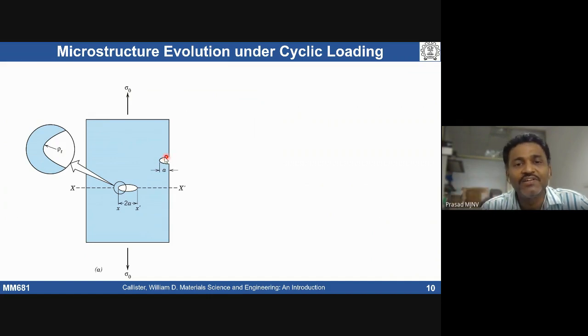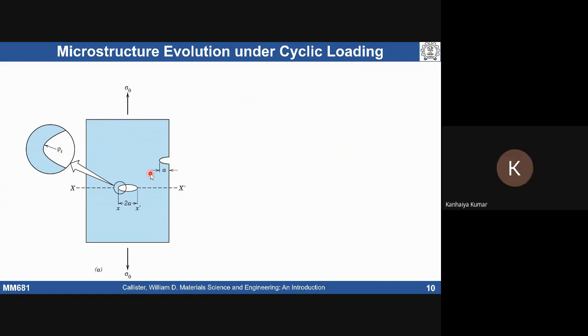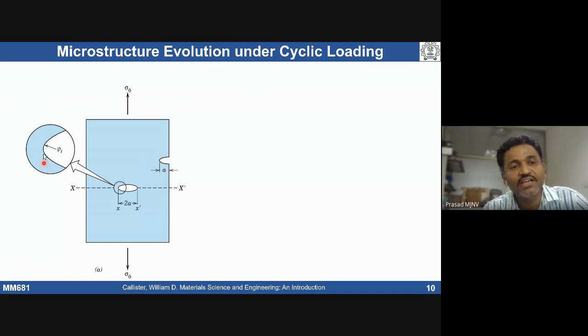Now assume that a crack has been formed on the surface. If I look at the stress in front of the crack tip, is it going to be higher or lower than sigma naught? I hope some of you already had a fracture mechanics course at your UG level. Higher, yes. That always depends on the radius of curvature of the crack tip. If it is a sharp crack, the radius of curvature is going to be different than if it is a blunt crack. Near the crack tip, the stress can be infinity if it is a very sharp tip.